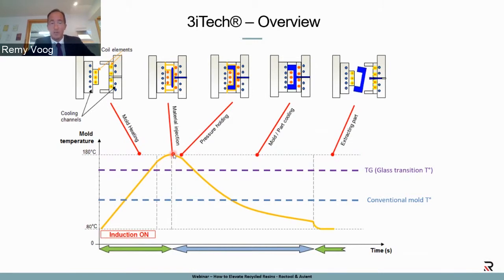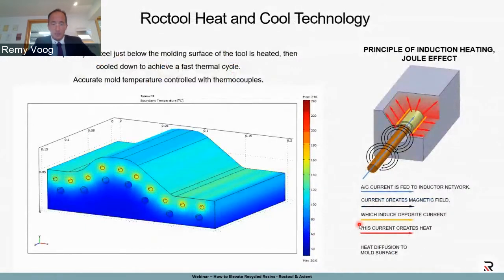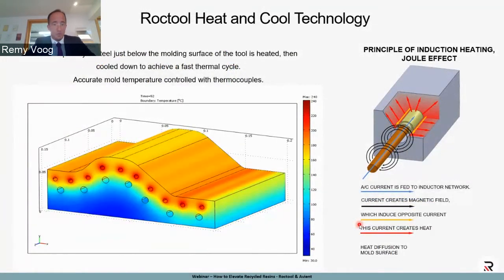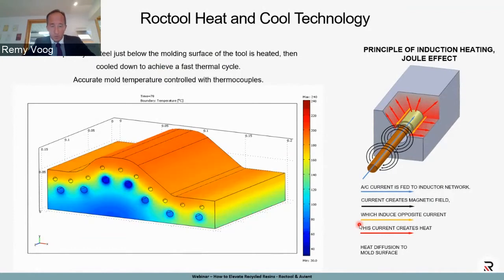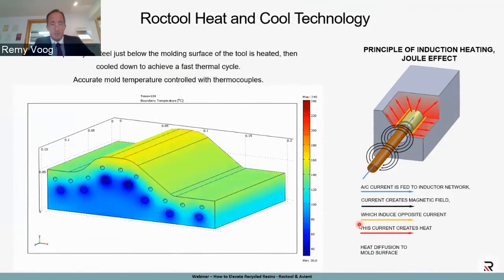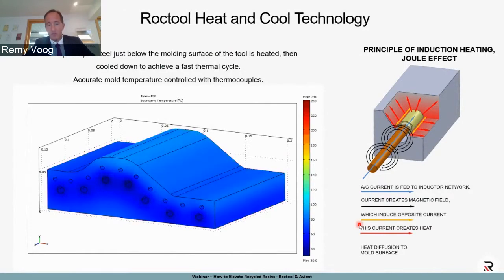And as I said before, if you give the time for the polymer chains to realign, you will decrease the anisotropy, and that's what we're doing here. You do what you have to do, and then as soon as everything is done, you go and cool down. So what does it look like inside the mold? The very important point here is that you have two different channels for heating and for cooling.